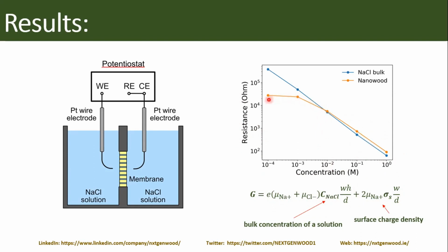And this is clear evidence that we come to this region where we have the nano-confinement effect. So we can clearly see that we have two regions here, bulk conductance and nano-confinement. This means that if we want to observe this thermoelectric enhancement, we should look at concentrations of electrolyte like less than 10 to the minus 3.